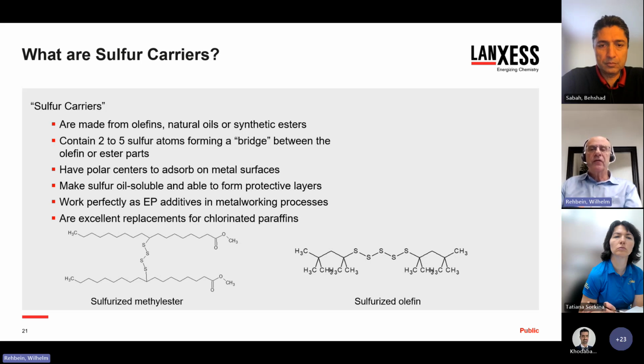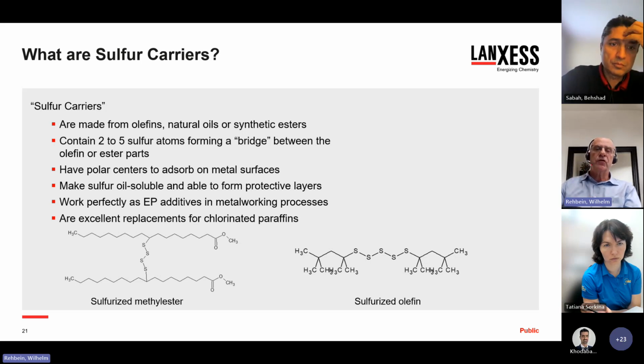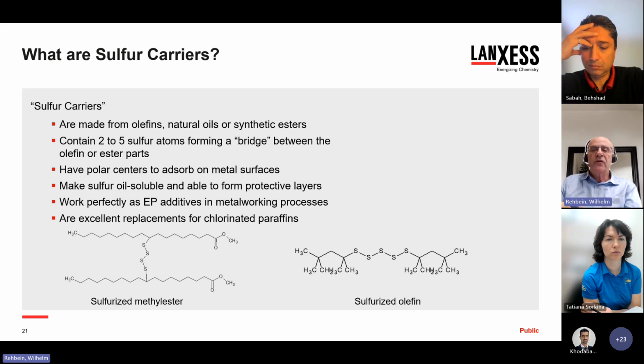They have polar centers, as I already showed on the previous slide. And with these polar centers, which can be oxygen atoms or the sulfur atoms itself, they can physically adsorb on metal surfaces. And by this, they make sulfur oil soluble and able to form protective layers, which protect metal surfaces from adhesive wear or galling. So they work perfectly as EP additives in metalworking processes and are excellent replacements for chlorinated paraffins.